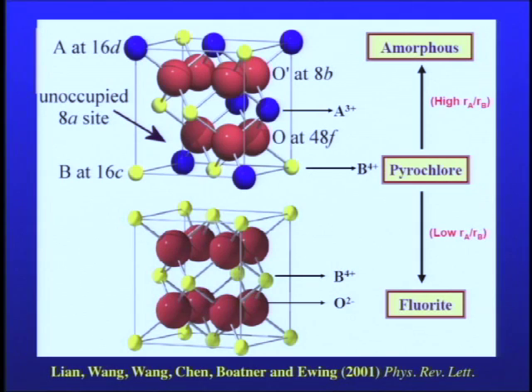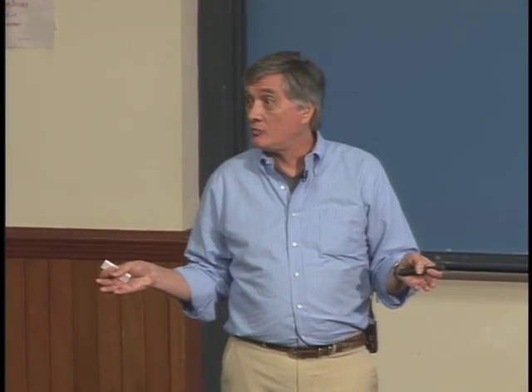But what's important from a radiation damage point of view, remember the cascade, when we have this cannonball go through the structure and everyone is separated from their partners, they have some choices. They could try to get back to where they were. They could organize themselves and their partners so that they make the pyrochlore structure again. Or they could only get part way. They could have disordering over the A and B sites and disorder the anion vacancy so it looks ordered, but if you looked at each person, you would see the wrong person dancing with someone else's wife, something like that might happen. This would be the fluorite structure. Or you just couldn't get back to where you were, and it would be amorphous.